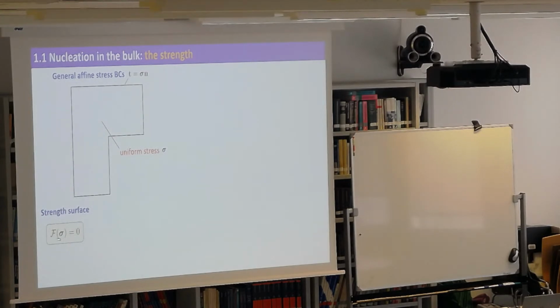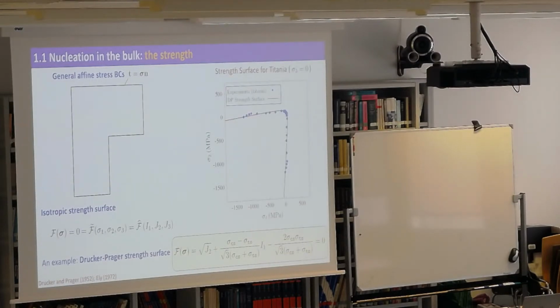So a surface in sigma equal to 0, that's a surface. And if you think about the material being isotropic, you expect the strength to be isotropic, so you have a surface that is isotropic and therefore representable in terms of invariants of the stress. And this is the formula for a classic strength surface. It was not derived as a strength surface. It was derived as a yield surface for soils, but you can use it for strength. And people have done experiments in the 70s and in the 80s. People working in ceramics, that's what they did, right? They subjected the specimens to a combination of constant stresses, the best they could. So approximately sigma 3 is 0, and approximately sigma 1, sigma 2 are uniform in the specimen.